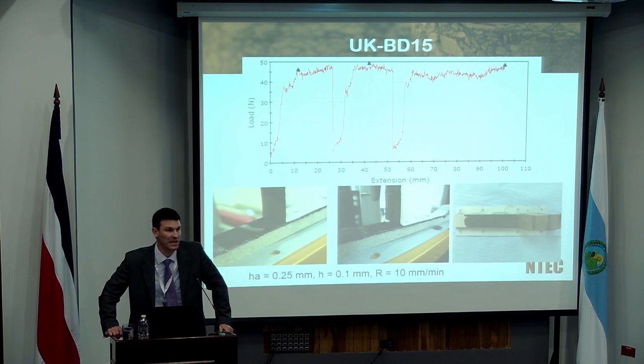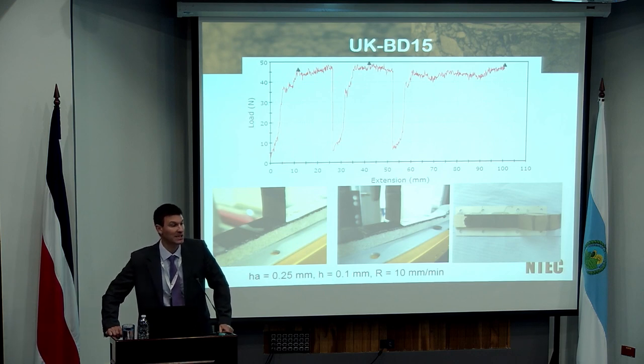It's an effect that you see in mechanical engineering when you use epoxy resins as well. It's when the material is stiffer than it should be in terms of being able to carry that load in terms of its propagation. It's not a problem because you can still get an average force and therefore an average fracture strength for that material. But I'm going to show you in a second how we can use time temperature superposition to reduce the variability, or at least those errors in terms of that crack jumping, by changing the displacement rate. So displacement rate is one of the parameters, obviously temperature is the other.